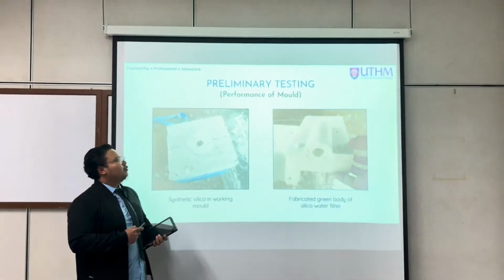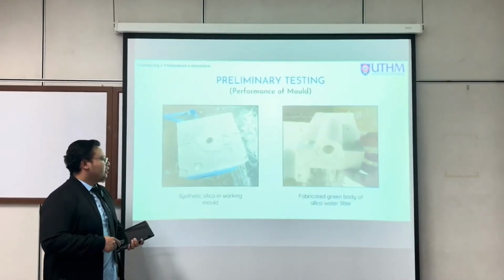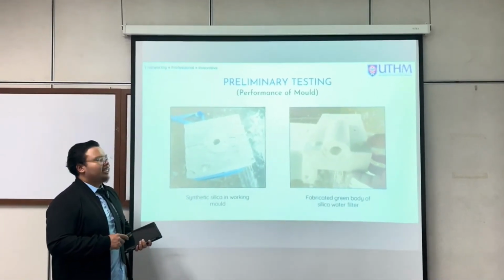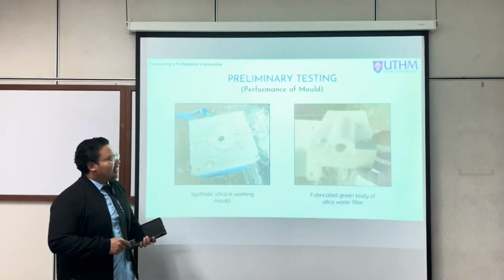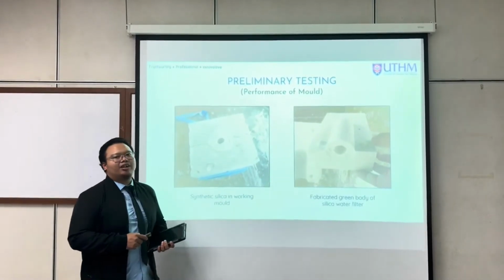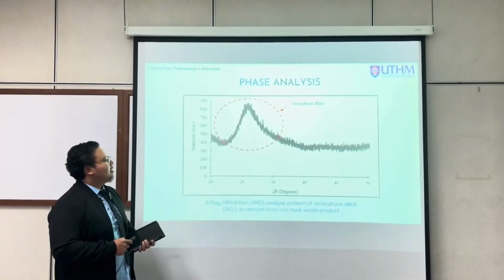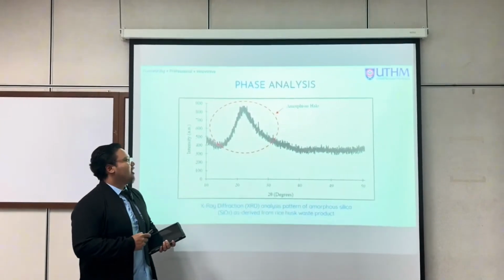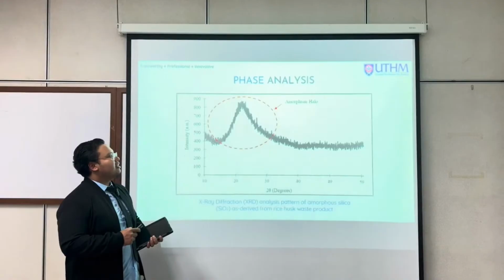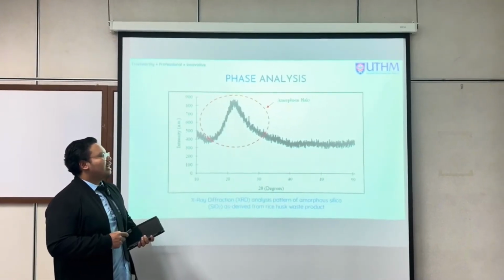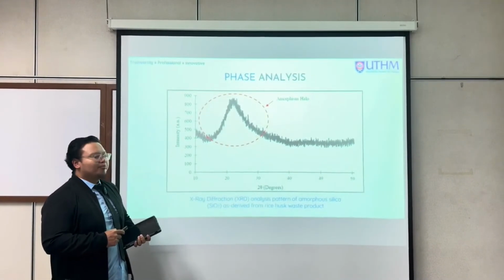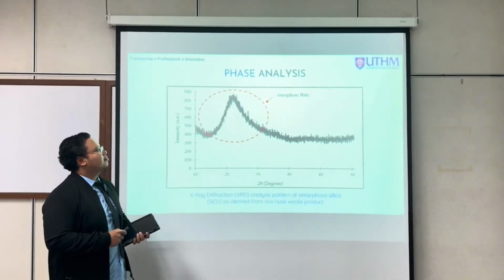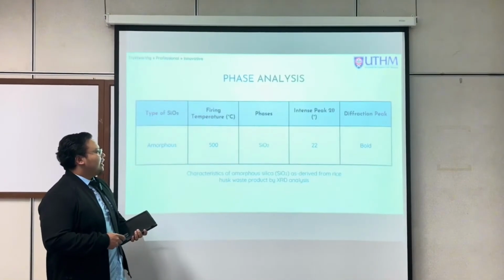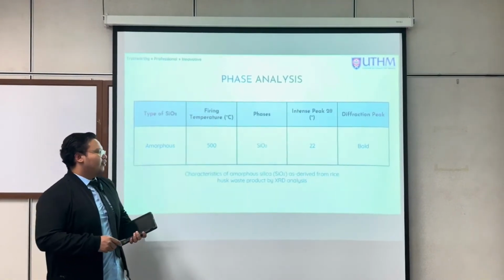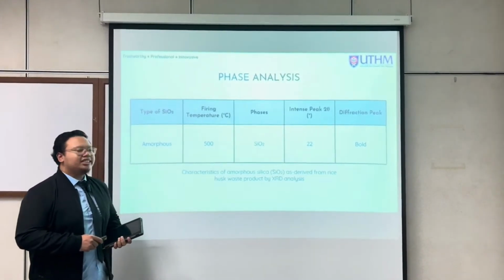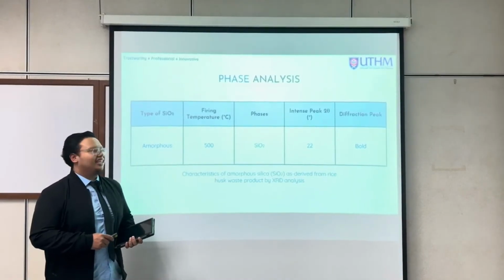For preliminary testing, which is the performance of the mold, we used the synthetic silica in the working mold, as shown in this figure. And these are the fabricated green bodies of the silica water filter. For phase analysis of amorphous silica, we can see the amorphous halo for the amorphous silica that was produced at 500 degrees Celsius. And these are the tables for the characteristics of amorphous silica derived from rice husk waste product by XRD analysis.